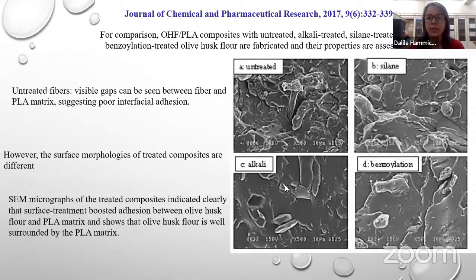As you can see on the screen, it is the comparison between the same micrographs of untreated and treated fibers using silane, alkaline, and benzoylation treatment. These figures show that for the composite prepared using untreated fibers, so without treatment, visible gaps can be seen between fiber and PLA matrix, suggesting poor interfacial adhesion. This presumably arises because of the incompatibility between fibers and matrix, as well as the presence of impurities on the olive husk flour surface.